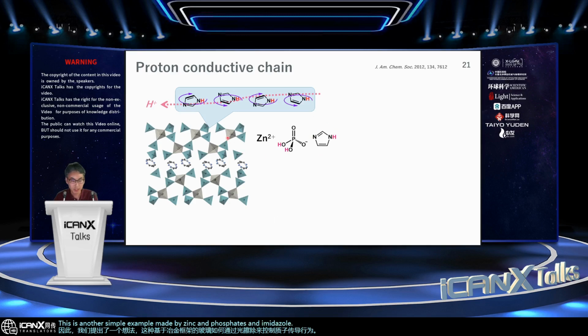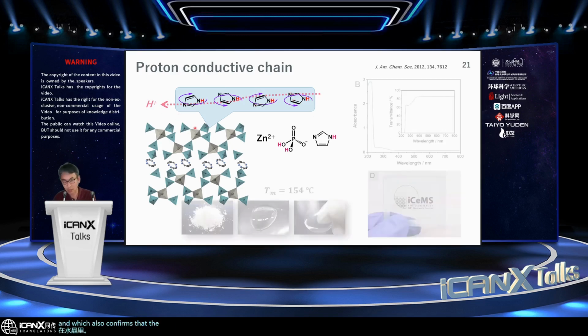And this is the crystal structure. Zinc and phosphates form this one-dimensional structure as shown here. And in between two one-dimensional structures, you can see disordered imidazolates. Imidazole is sandwiched in the structure. As indicated by this disordering, this imidazole in a sandwiched fashion has very high rotational motion in the crystals, which also confirms a very high proton conductivity.